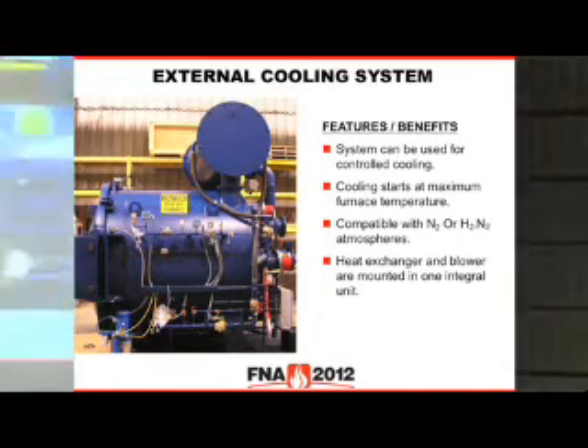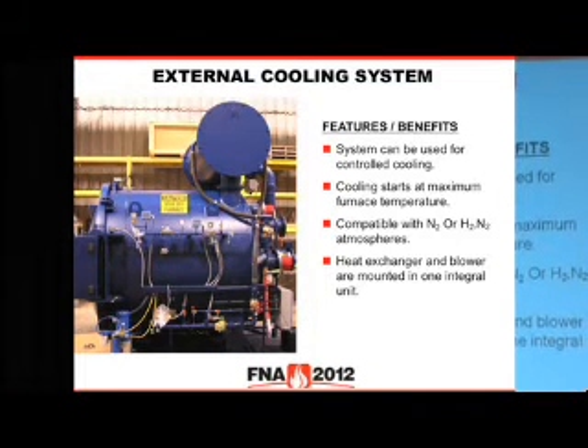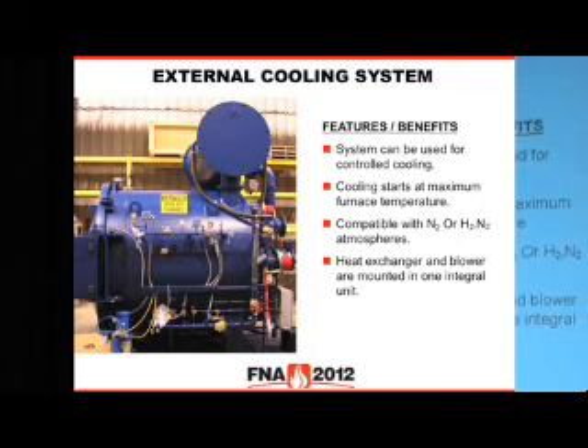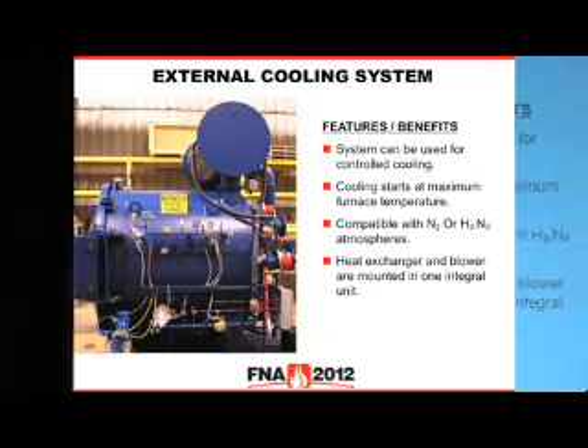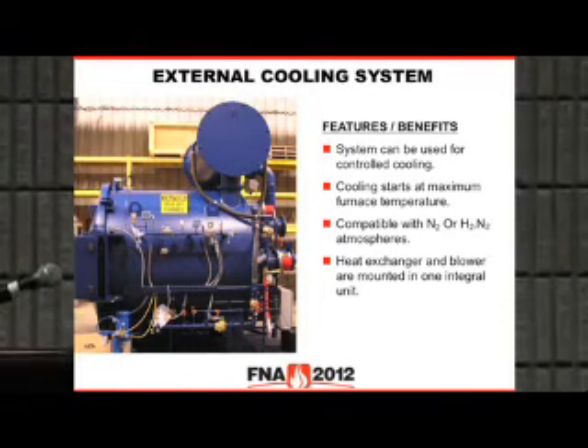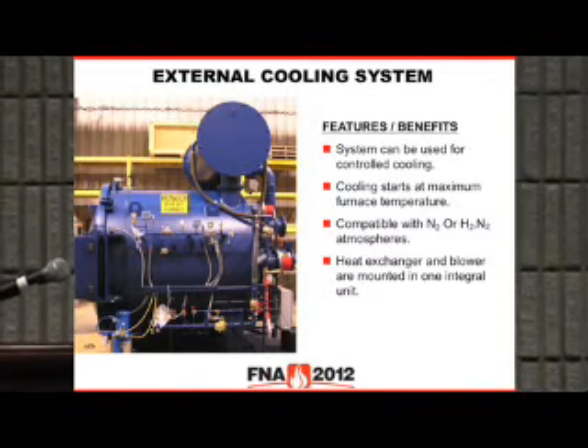And the other thing we can do with the external cooler that we really can't do with the intracool design is if you want a slow cooling rate or a controlled cooling rate, we can actually put a VFD on this blower and actually cool at a rate. Whereas the intercool system is more like a high pressure quench furnace where you start cooling and you're not going to stop. You're just going to keep on going. So this particular unit has more flexibility with that.